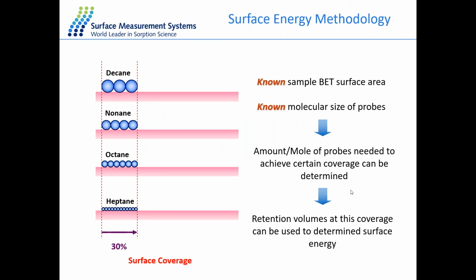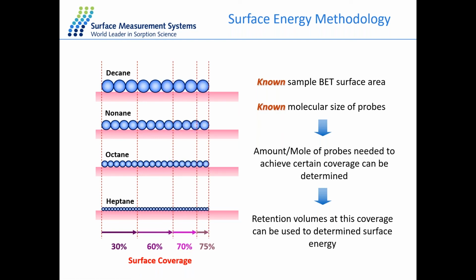So prior to running the surface energy experiment, there's a few things that we need to know. First is our BET surface area. As we've seen, we can carry out BET surface area using the iGC-SEA, or alternatively, if you have the value known, we can just plug that into the system. We also need to know the molecular size of the probes. With the iGC-SEA, we have a database, a library of different probe molecules with their physical information. In this case, we will have some known properties of your polar probes and your non-polar probes. So what we need to do now is look at the system, and we're now able to calculate the amount of moles or the percentage that we need of our probe molecule to cover a certain coverage of the surface of our sample.